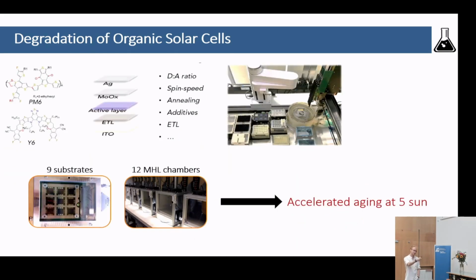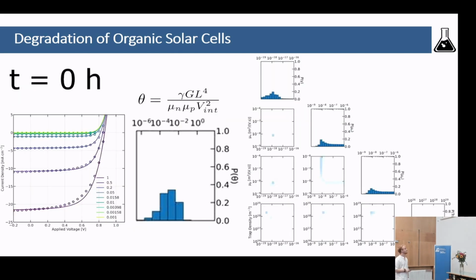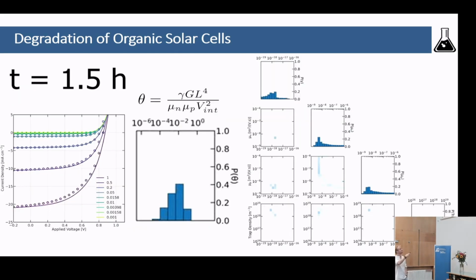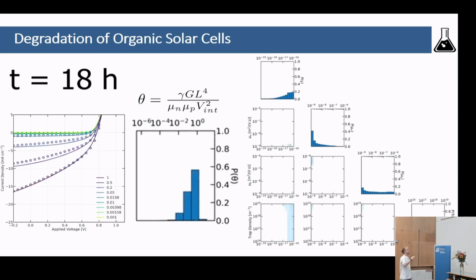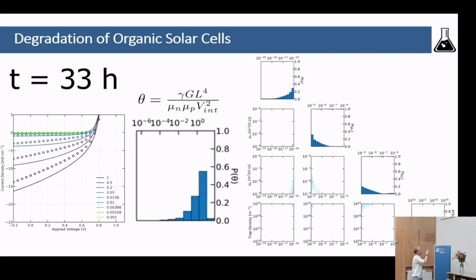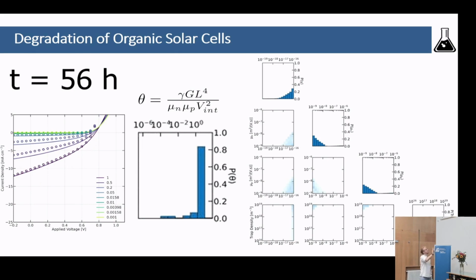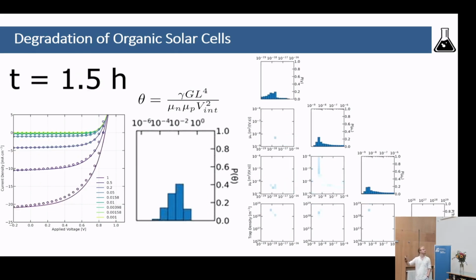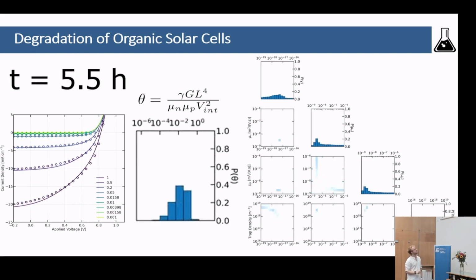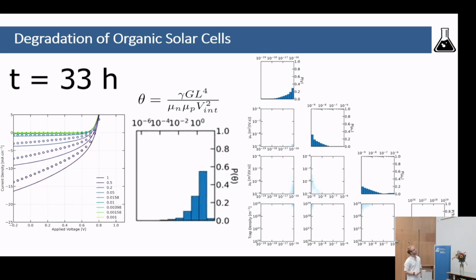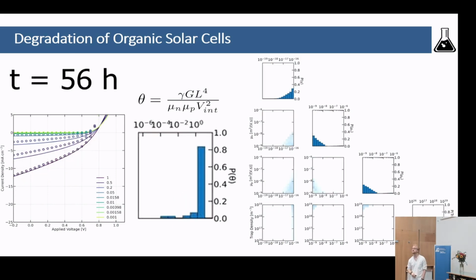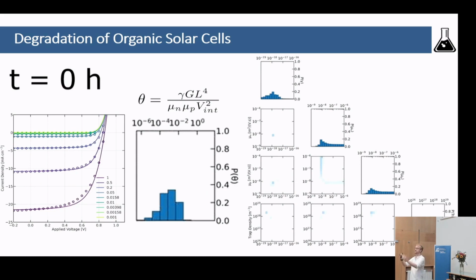Now this is all nice. This was all on simulation, but I want to show that it also works when you look at experiment. So I took some PM6:Y6 data that were aged in our lab, and I also tried it, and you can fit the light intensity dependent data. And you can again see how those figures of merit move around. You again don't get a very nice distribution on some of the parameters, but you can really see how those figures of merit change, and they give a very unique solution.